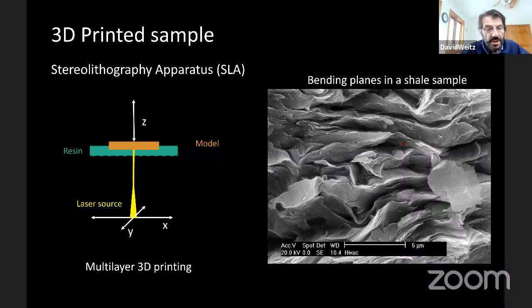The actual material that we use is something that's printed with a stereolithographic technique. Basically, you expose layers of the sample, and the exposure of the laser causes the resin to solidify, and you print layer by layer. The company that makes these printers is just a local startup company. Again, one of our former lab members is the person who designs the resins for it, so we know him well. And what's nice about that, because you're doing 3D printing, you're sort of getting a layering effect to begin with.